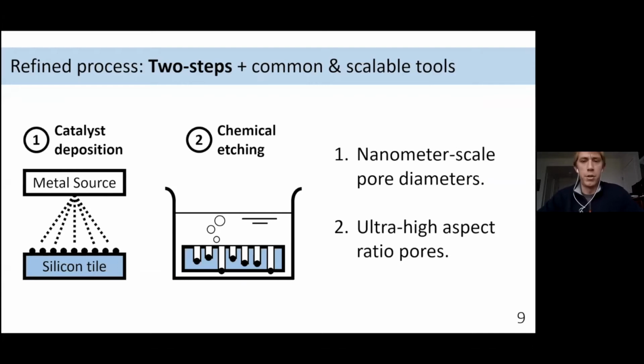Really two main advantages compared to the status quo techniques available today in industry, things like electron beam lithography followed by reactive ion etching, for instance, are that we can obtain much smaller pore diameters relative to these more controlled microelectronics-type approaches. And again, we don't really care about where these features are placed, only that they're highly dense and are relatively homogeneous in terms of pore size and aspect ratio.